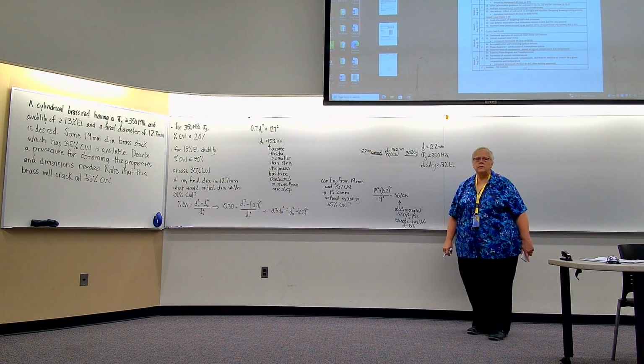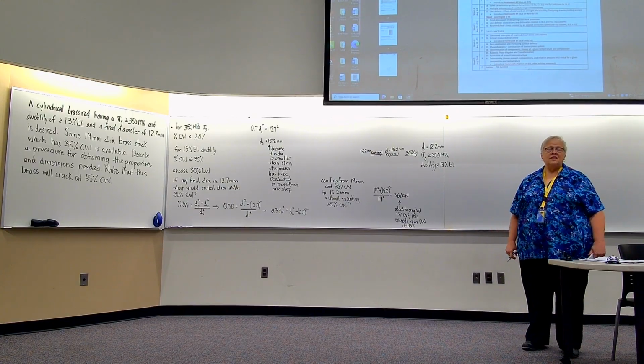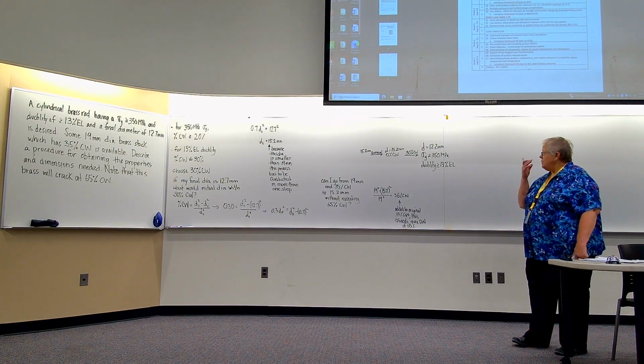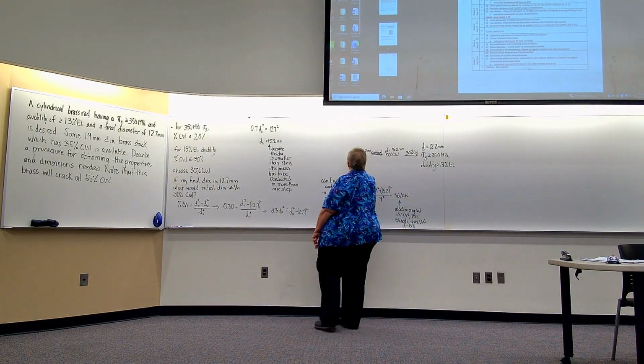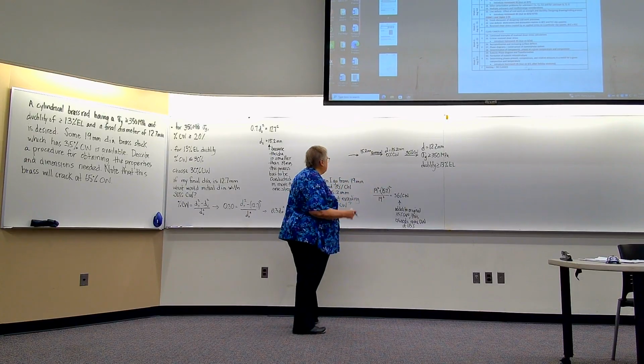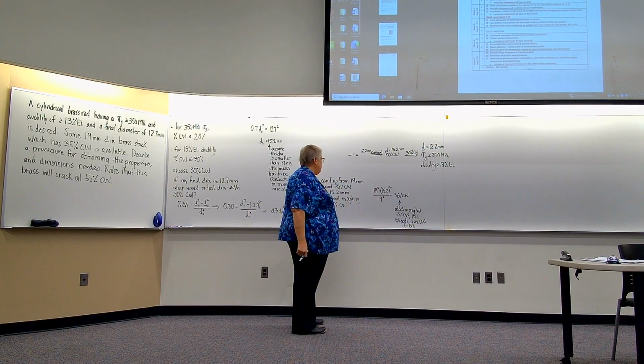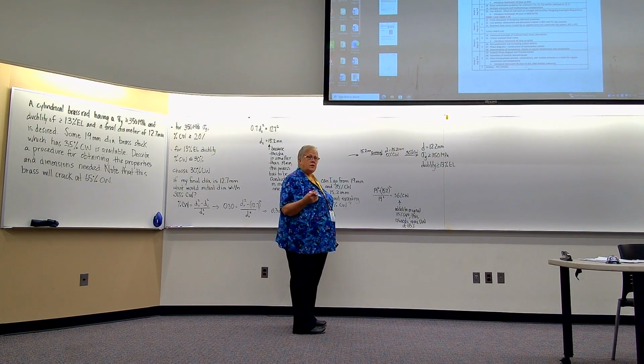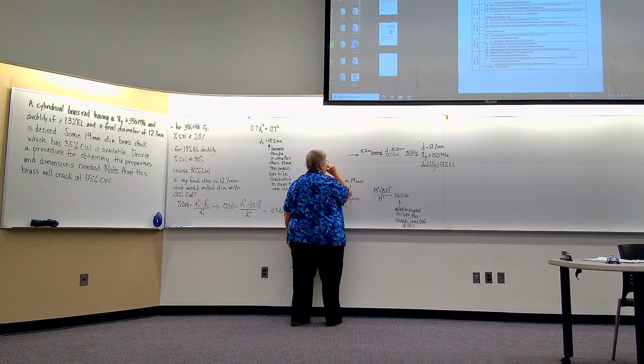We do know that we'll only need one more step. We're very close. So what I would do then is I would say, okay, well, this step then, how much cold work do I want to use? Well, really, anything less than 30. Let's go 25. Now, this again is one of those multiple right answer problems. I'm just choosing 25 because I don't want to choose 30. It seems like I'm getting close to breaking, but I want as much as I can, so I get this done. You can choose anything between 0 and 30. I'm going to choose 25% cold work.